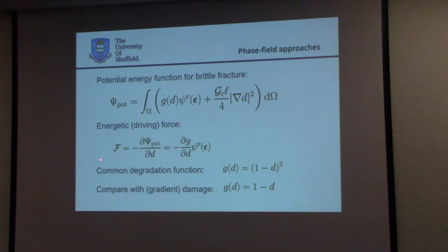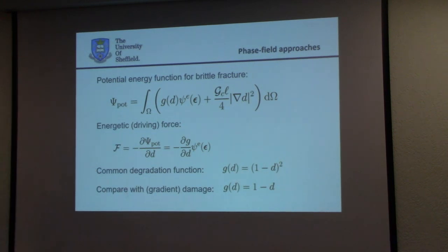Now the energetic driving force is the derivative of the potential function with respect to the phase field parameter, and this is the derivative of this degradation function with respect to d times psi. And here you see this one must obey certain continuity requirements also, and that's imposed on this.